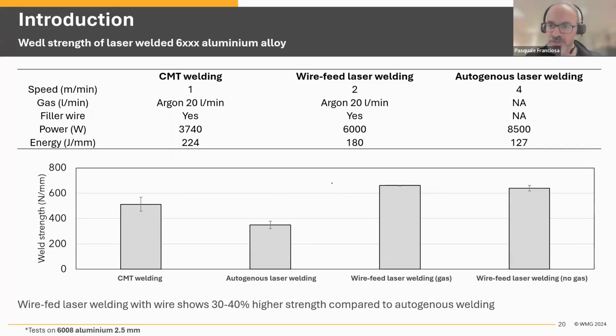This was a comparison between different welding processes. CMT on this end, then laser welding with addition of a filler wire, so it's a wire-fed welding process. And then autogenous welding, so only laser, without even shielding gas. And you can see the gap. There is almost a 30 to 40% drop in strength when you are welding those alloys fully autogenous. And a 30% drop in strength from a certification point of view is automatically a no go. The end user will never accept that level of strength because it's not satisfactory.